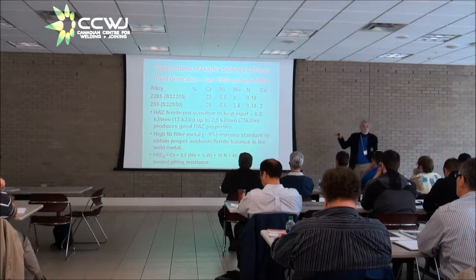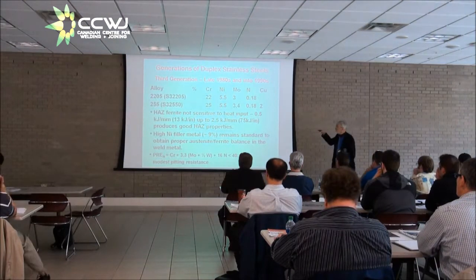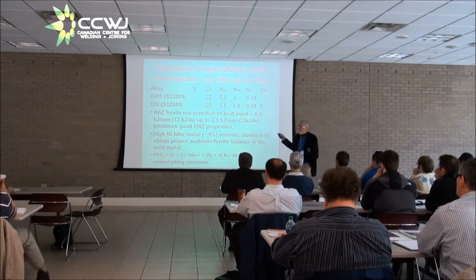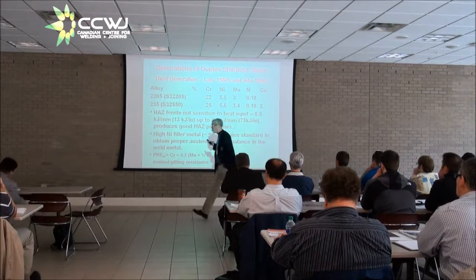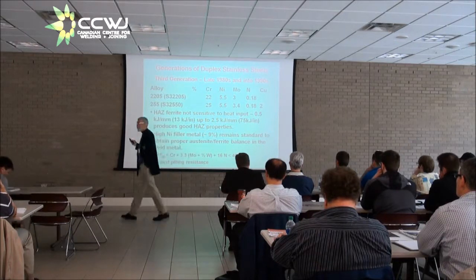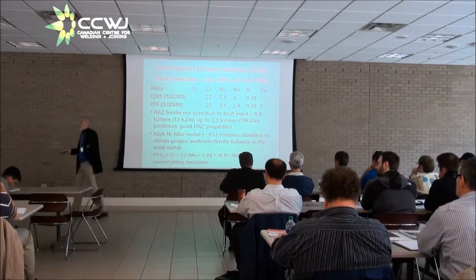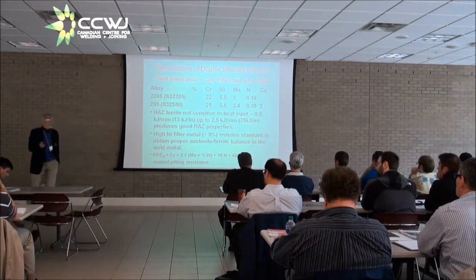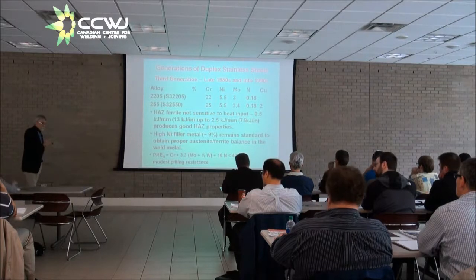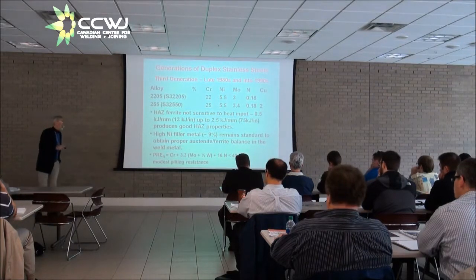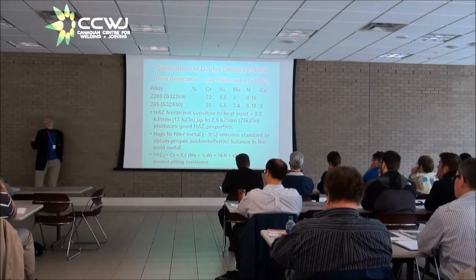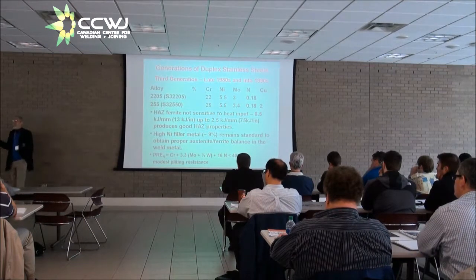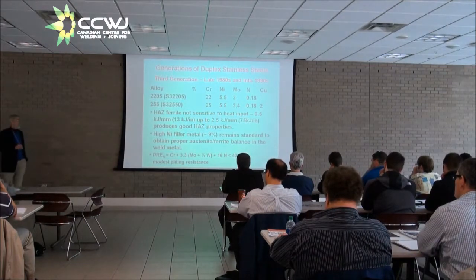Now, the heat affected zone is not very sensitive to heating. You can go from a half kilojoule per millimeter to 2.5 kilojoules per millimeter and still get good heat affected zone cracking resistance. A big advance. Partly for historical reasons, but partly also to improve the toughness of the weld metal, the filler metals still tend to be high in nickel.